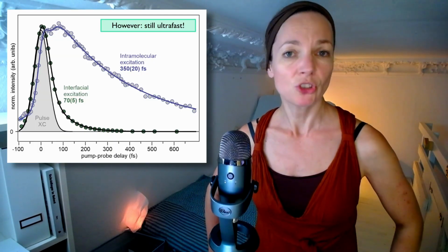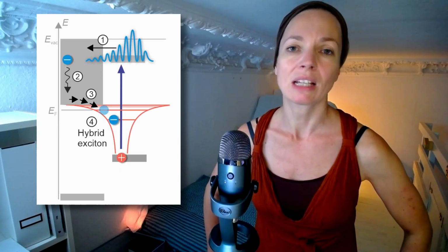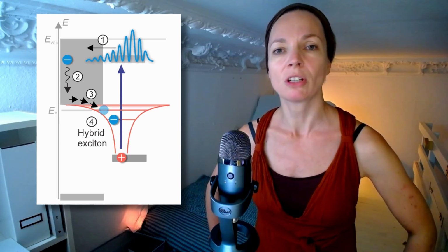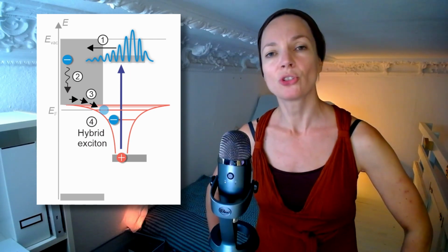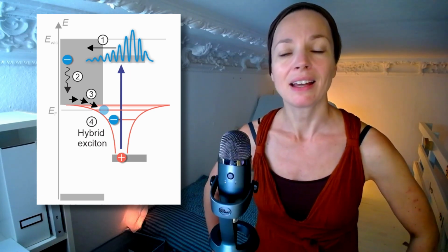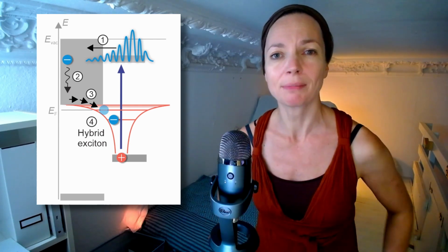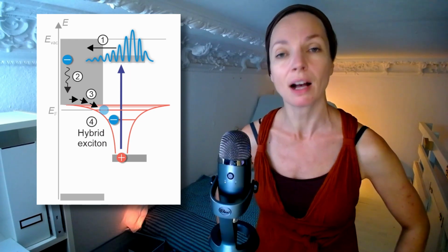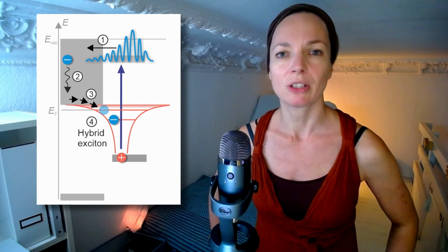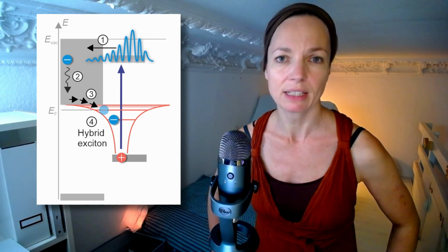And with these experiments, we could show that indeed there is very strong coupling of the excited state of the molecule to the zinc oxide conduction band, and this is not the reason for the reduced charge separation efficiency, but in fact electrons do enter the zinc oxide, relax really quickly to the conduction band minimum, and then they return to the surface on a 100 picosecond timescale and get trapped, not in trap states, not in defect states, but in hybrid exciton states that have a lifetime of 5 microseconds, which is really long, and a good reason for zinc oxide not working in light harvesting applications.